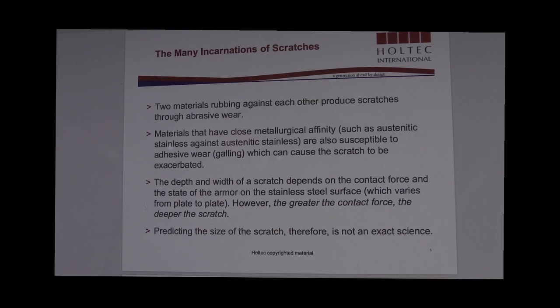Moving to slide number 5. So what are the mechanisms by which these scratches occur? When we talk about the MPC and the MPC shell, there are two basic mechanisms that we've observed and noted as the physical causes of these scratches. The first is simple abrasive wear, when you have two materials rubbing against each other. Usually there may be a harder material that impinges or rubs against the other material, in this case the MPC shell, under some contact load. That is one form of wear and one cause of the surface scratches.